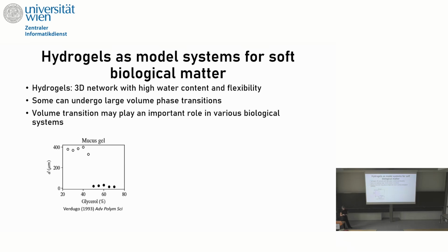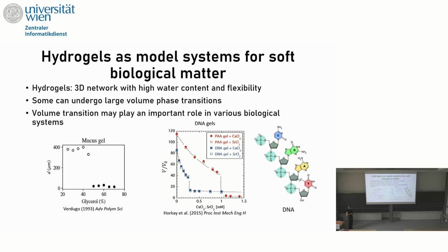Its swelling and deswelling in the cellular system is related to divalent and monovalent ion exchange, but in this case, this is a solvent quality example. When we get to a composition of 50% water and 50% glycerol, the gel collapses and loses its volume.